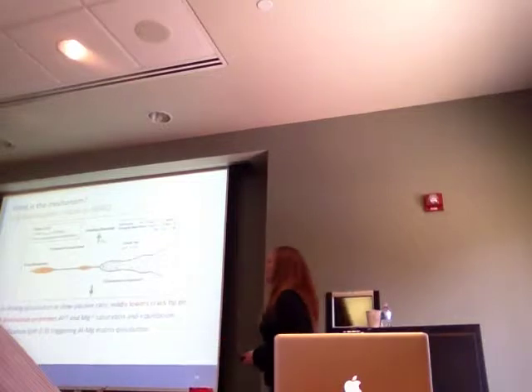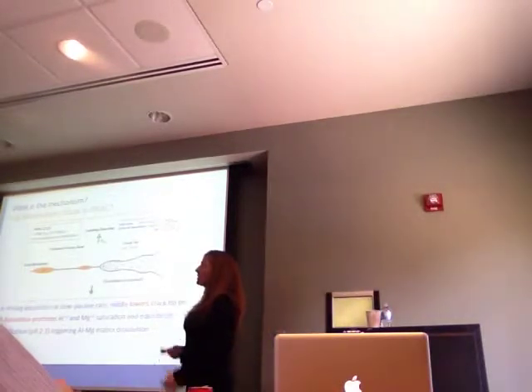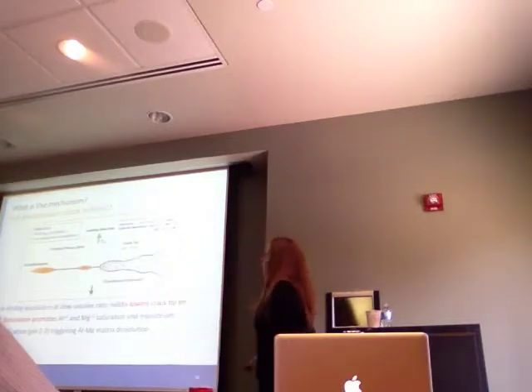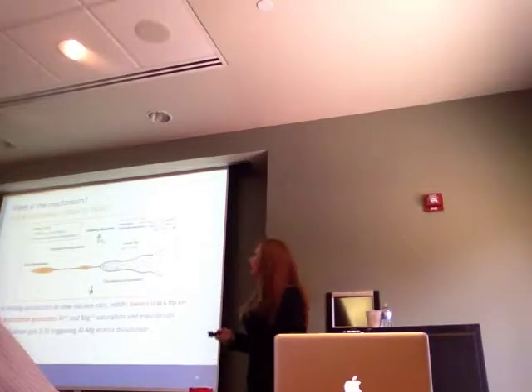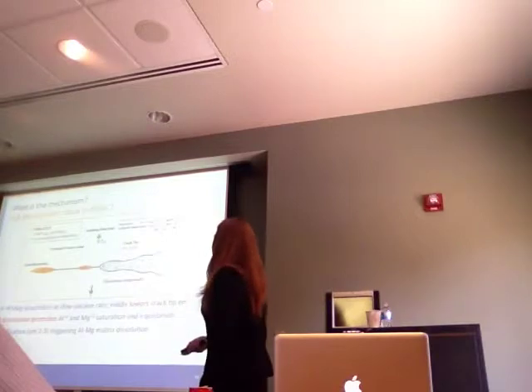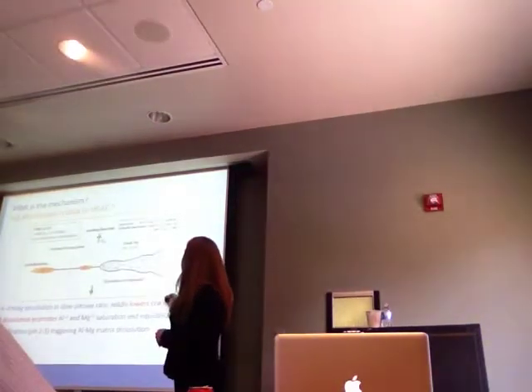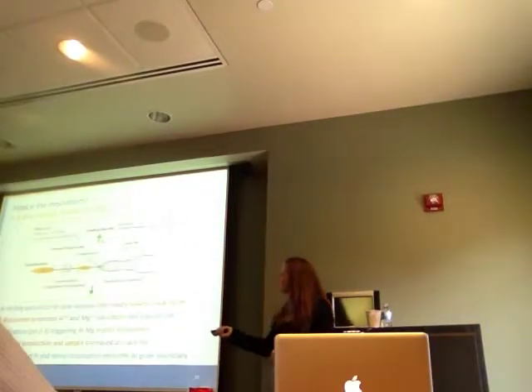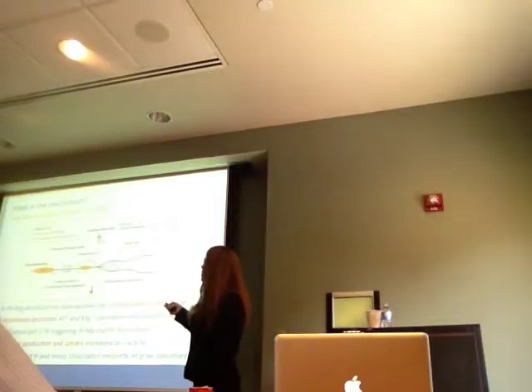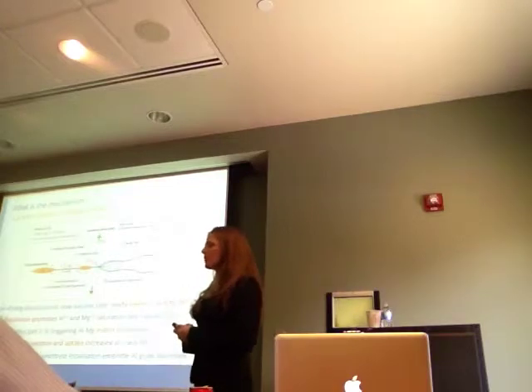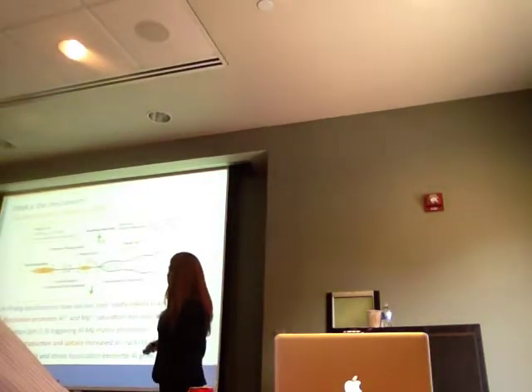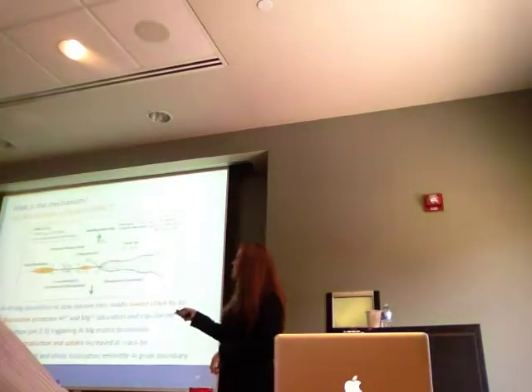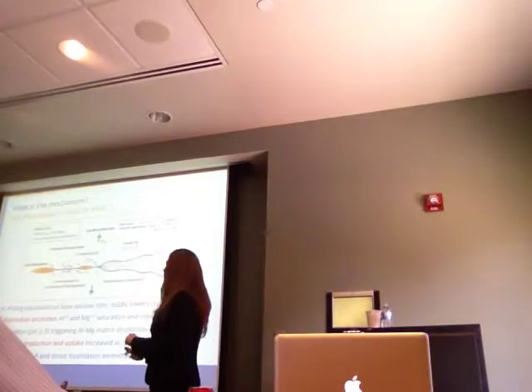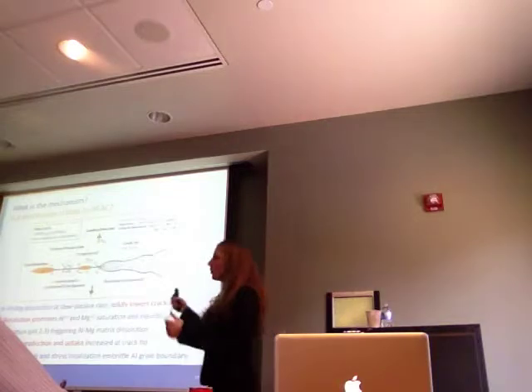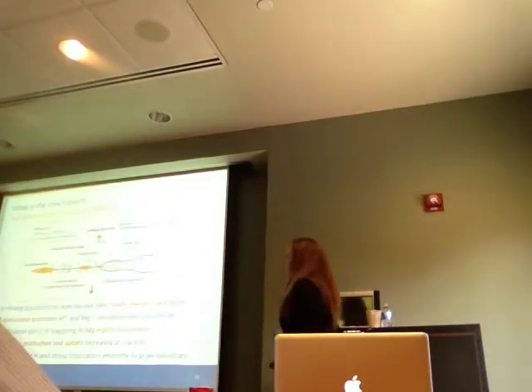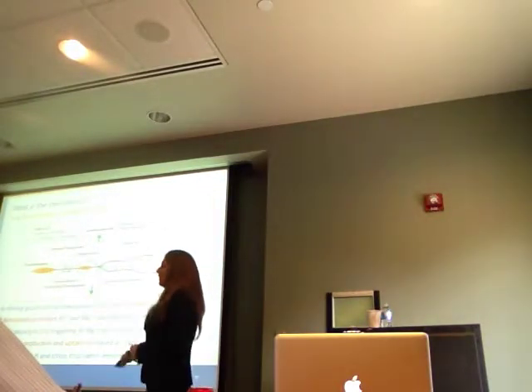And of course, we believe it's the beta phase. So when this beta precipitate dissolves, it saturates this crack tip with aluminum 3+ cations and magnesium 2+ cations. These cations undergo hydrolysis and cause the crack tip pH to go to 2 to 3. This very highly acidic crack tip then causes cathodic hydrogen production and uptake. And once hydrogen is in the microstructure, it can diffuse to the locations of high stress triaxiality. That can be either the matrix and the beta interfaces, or the region between the precipitates where you have constraint between the particles. So you have a nice stress concentration at the edges of the beta, or the region between where you have the constraint. And with the high hydrogen concentration and the stress in that region, you're able to embrittle the grain boundary.